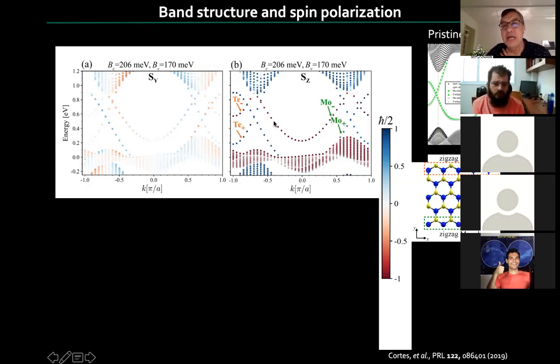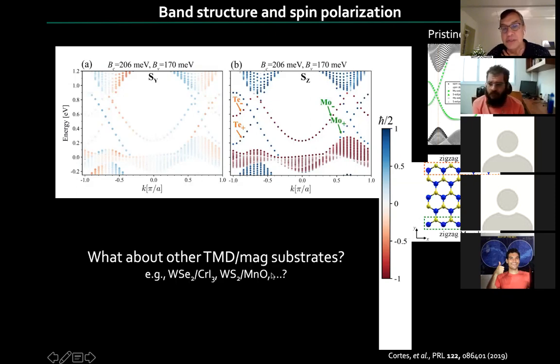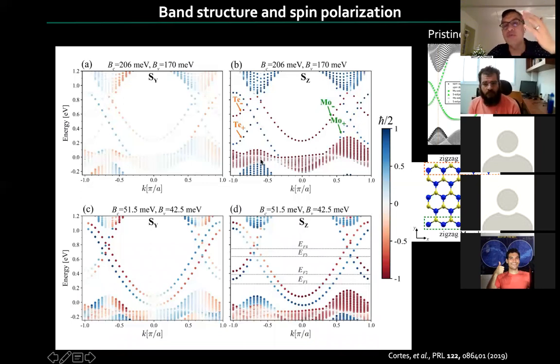Now, of course, this is molybdenum telluride on europium sulfide, but you can imagine different materials. There are many different materials nowadays among the TMDs, and for the magnetic exchange you have chromium triiodide or manganese oxide or whatever, and that will produce different exchange bias, different gaps, and so you have a whole zoo of these. To illustrate that, imagine that I take the same molybdenum telluride, but I reduce the exchange bias, because I put it on a different substrate. And so I have the same bulk structure, but the splitting of the edge states is less because the exchange bias is smaller. But it has the same peculiarities. Notice that here the white component is darker than above because the exchange bias is smaller. So that means that the Z component is less strong and the Rashba is kind of more on equal footing.